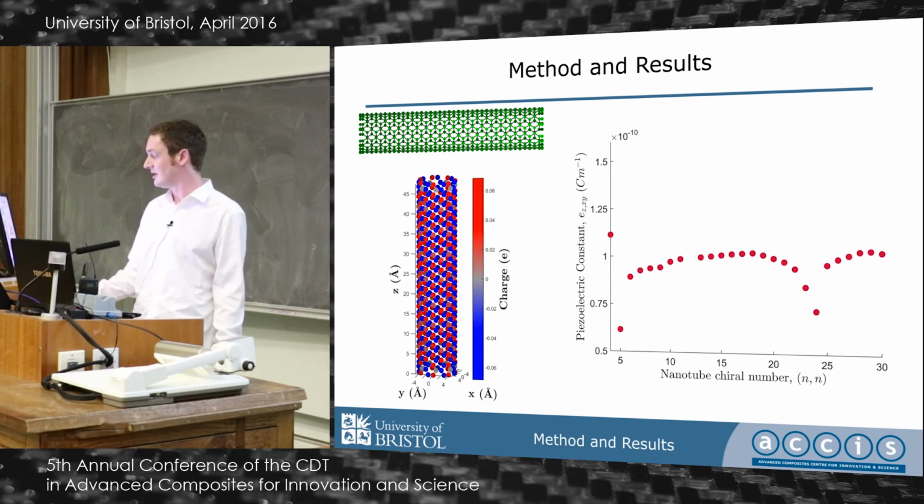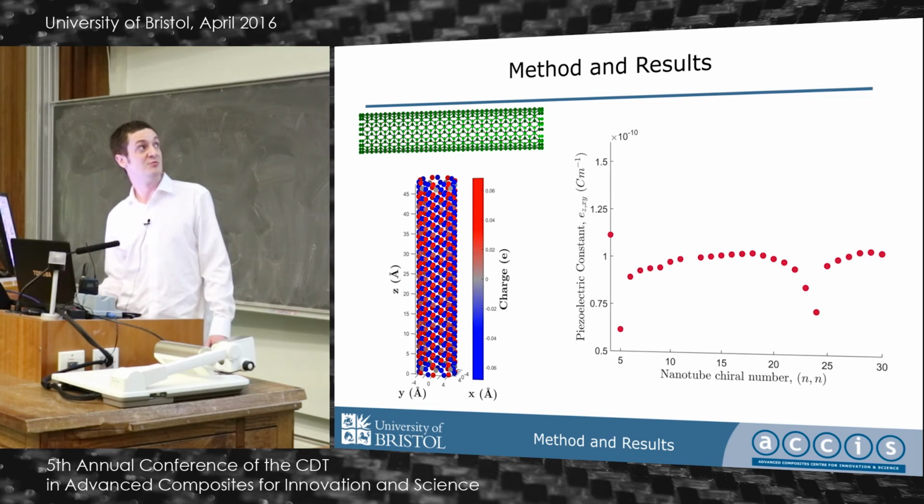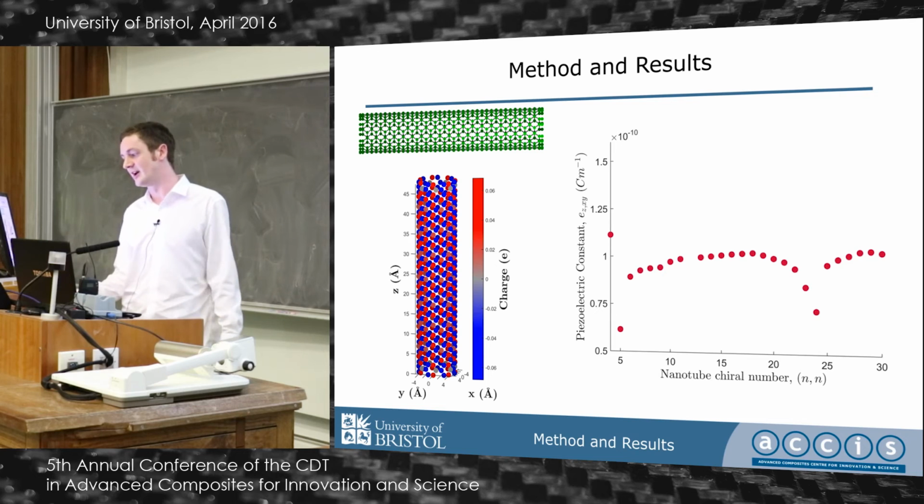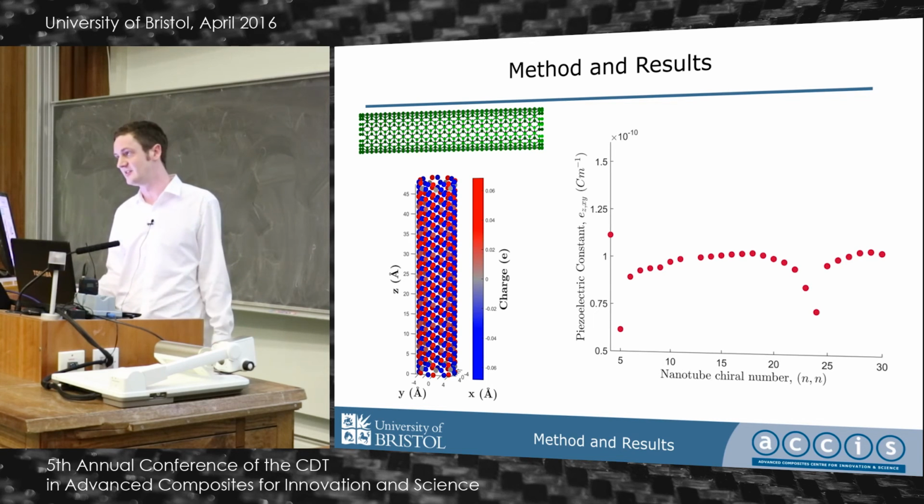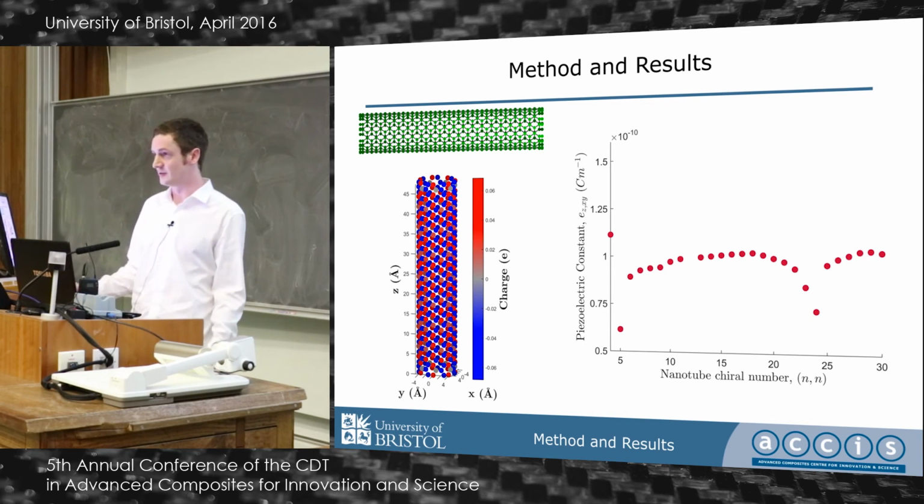And then from that, we can do some various bits of physics, which I did for a boron nitride nanotube to generate piezoelectric tensor coefficients. We found we could get a reasonably good result from that compared to higher fidelity modeling such as DFT. The difference was we could do it for 100,000 atoms instead of a dozen.